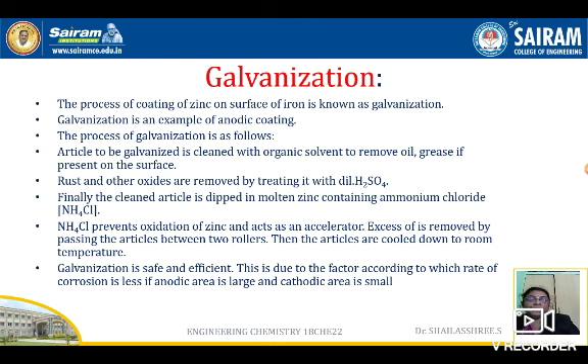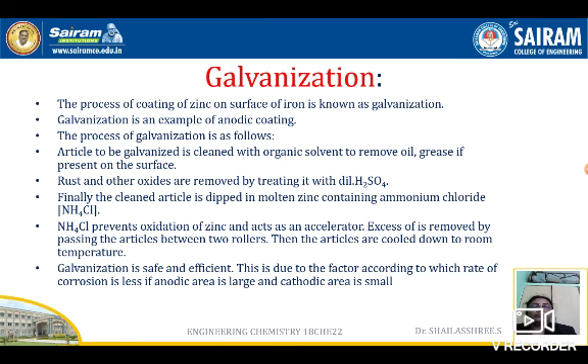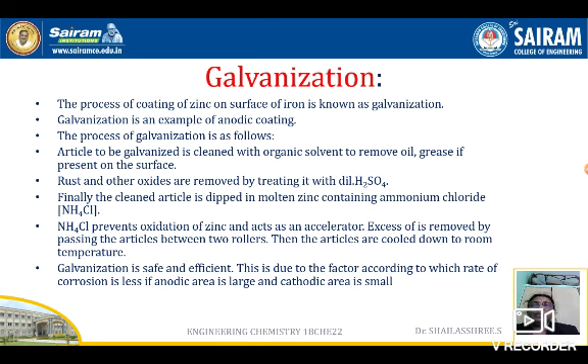The process of galvanization is as follows. First, the article to be galvanized is cleaned with an organic solvent to remove oils, greases, and other organic impurities. Next, the metal is treated with dilute acids such as HCl or H₂SO₄ to remove scale-like impurities. Then, to obtain a smoother surface, the metal is coated with ammonium chloride and zinc chloride. Finally, the article is dipped in molten zinc at a temperature of around 430 to 475 degrees centigrade, and the excess zinc is removed by passing it between rollers.